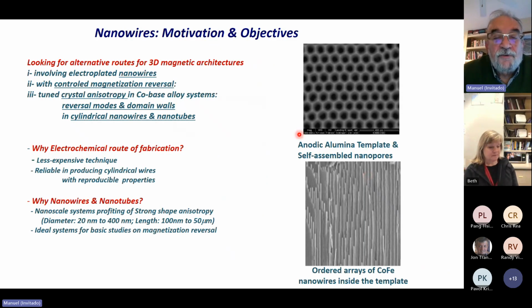We have been working for years on these families of cylindrical nanowires fabricated by electrochemical routes. First we prepare the alumina membrane by anodization, a controlled anodization process. Then, once we have these holes in the membrane, we fill the holes by electrodeposition with the metallic magnetic nanowires. This is the origin of why we started to work with this electrochemical technique: it is less expensive in comparison with other techniques to prepare nanowires, and it is reliable to produce cylindrical wires with reproducible properties.